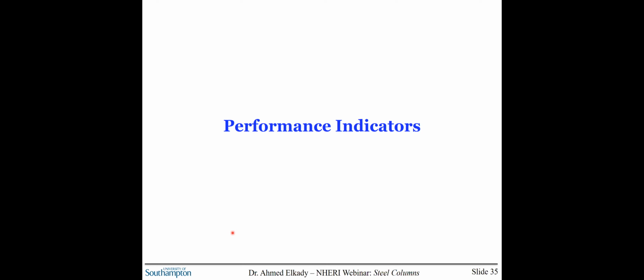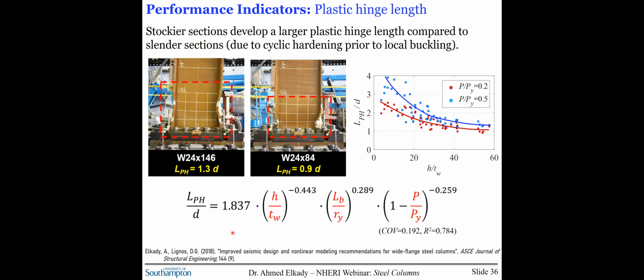Using the parametric data, again, we were able to conduct regression analysis and develop equations to predict key column response indicators. This includes, as you see here in this slide, the length of the plastic hinge region at the column base. This regression equation essentially captures the fact that stockier cross sections, the ones with a stockier web, in this case h/t web, will develop a larger plastic hinge length compared to a more slender column, due to the fact that local buckling is delayed and a large amount of cyclic hardening is developed that keeps propagating plastic strains to higher elevations.